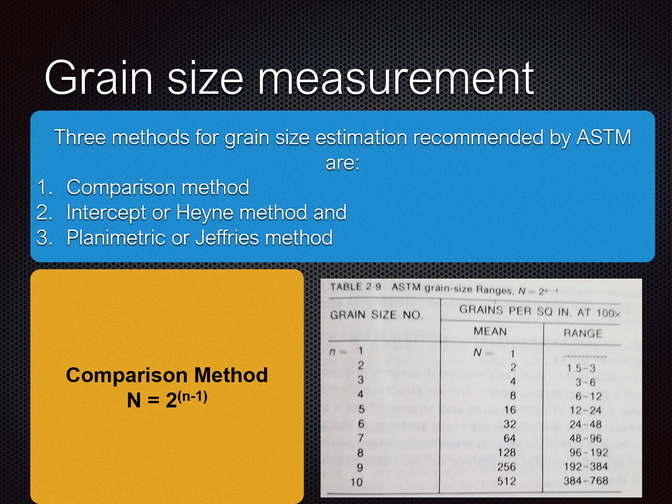Under the comparison method, the specimen must be properly prepared to reveal the grain structure, which is photographed at a magnification of 100x. It is then compared with the series of graded standard grain size charts, ASTM E112-63. By trial and error, a match is secured and the grain size of the metal is designated by the number corresponding to the index number of the matching chart.